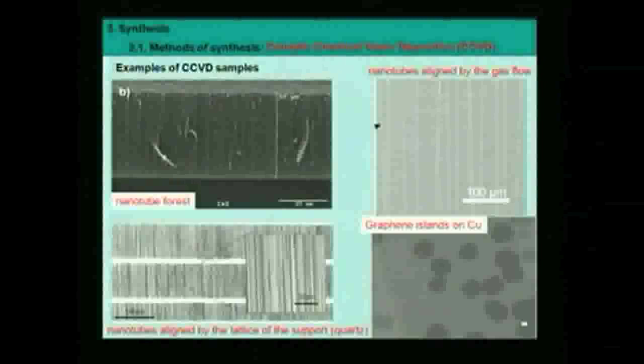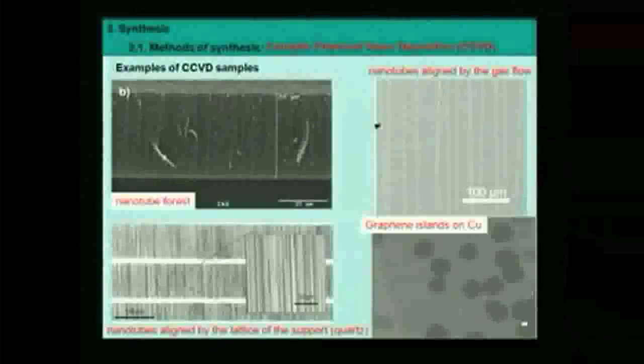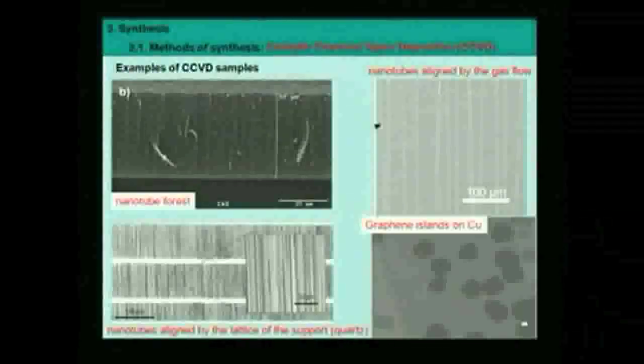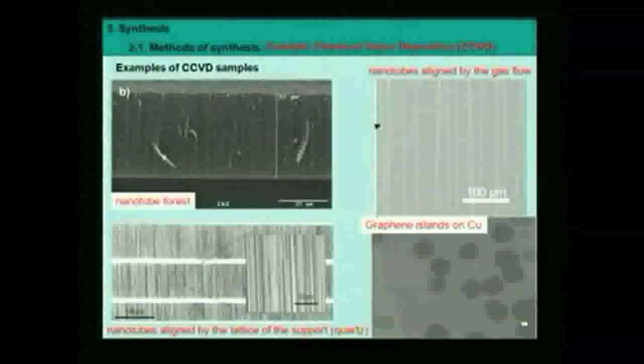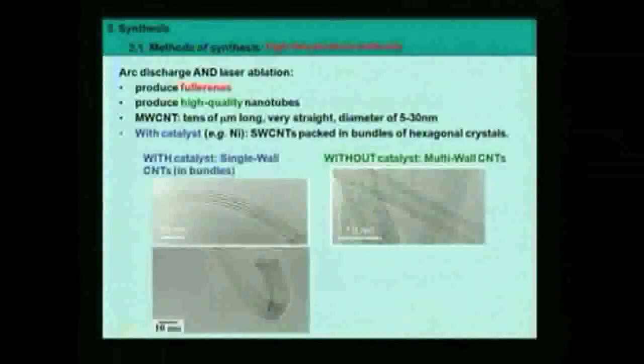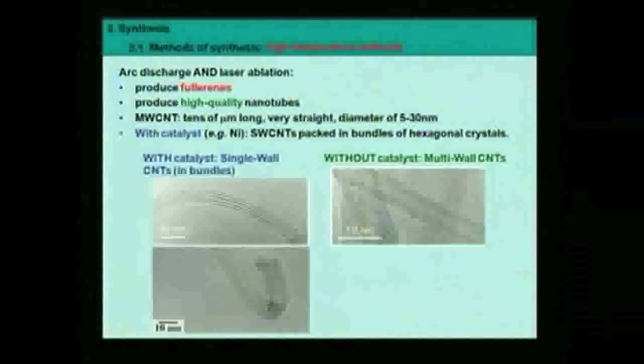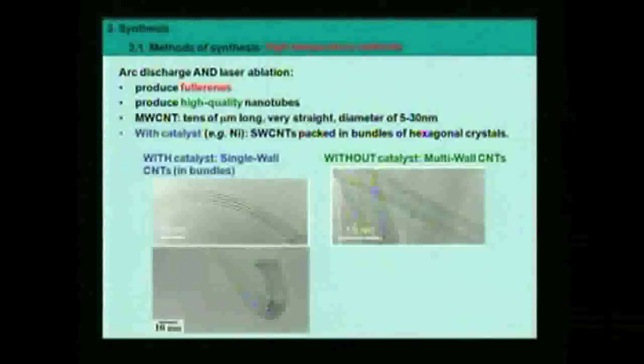The good thing with CVD is that the catalyst is at the beginning localized at the surface of the support. It means that at the end the catalyst is either mainly here or mainly here, but there is very little catalyst in between. Since the catalyst is localized, it's easier to remove it, mechanically, physically, not chemically. On the contrary, for high temperature techniques, like those ones, those are just very good pictures. But usually, if you look a bit around, there are many metal particles everywhere. And here, it's really difficult to get rid of them because they are everywhere. Okay?